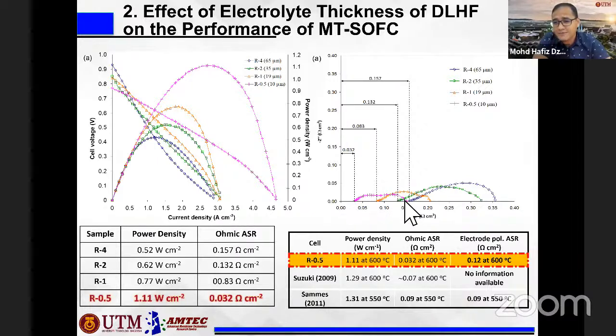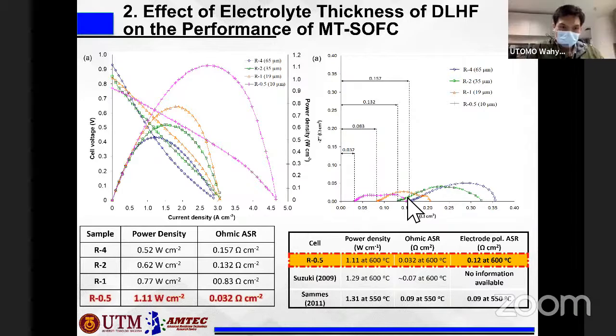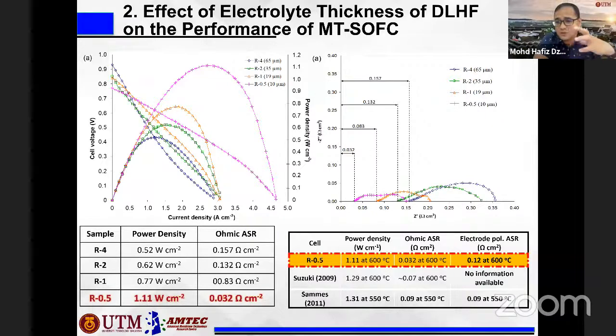So another resistance comes from the activation polarization and also concentration polarization. Normally, if you have better equipment, you can actually find the two semicircles. It's a very nice semicircle. But because of our setup, probably we have some issue, so we cannot measure the two semicircles very nicely. You can see there is some shape, but it's hard to determine where the second and third intercepts are. But the distance from the first to the last intercept is the polarization contributed by the activation and concentration.